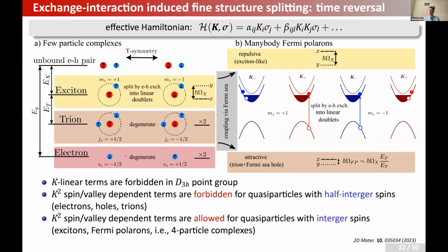Indeed, for instance, if you deal with electrons or with the trions, you can never make any combination of two different spin states or two different valley states that would be even at time reversal. Always time reversal brings your, say, spin up state to spin down state, one valley state to another valley state. Doesn't matter which linear combinations you take. However, for excitons, it is not so, because the spin is integer, and from these integer spin configurations, sigma plus and sigma minus, or momentum component +1 and -1, you can actually create the states that are linearly polarized, say X and Y polarized, that are even at the time reversal. So the time reversal doesn't mix those states.